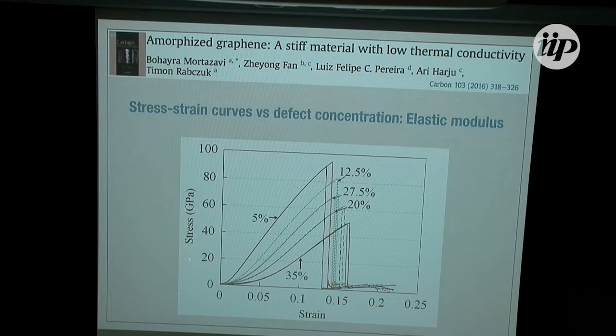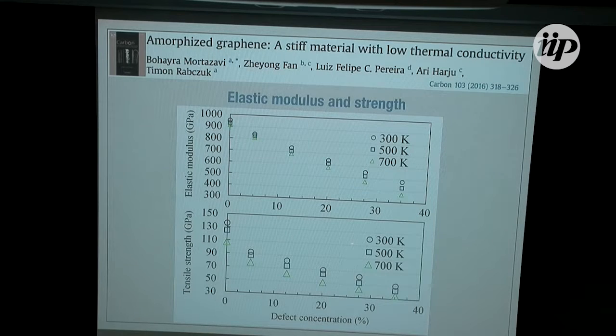When we calculate the stress-strain curves as a function of the defect density, we see that as we increase the defect density, the failure strain decreases. So the material starts to break sooner, and it fails at a lower strain. Okay, so we also look at how it depends on temperature.